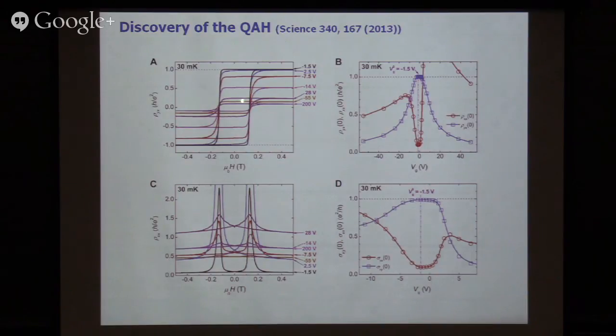So this is the more detailed experimental data. As you sweep the magnetic field, you actually see a hysteresis loop in an anomalous Hall material. You see this all the time. Except here, there's a plateau at H equals 0, at 1 in units of h over e squared. But when it's switching from the positive domain into the negative, opposite-pointing domain, at the same time, the longitudinal resistance actually has a peak. There's some interesting theory which could explain it. But that still looks a little bit like the Hall effect.